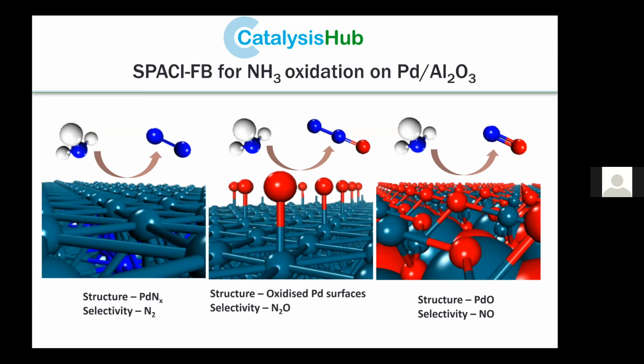It was found in a previous paper that under reaction conditions, palladium nitride is formed and is thought to be the selective phase. This palladium nitride phase is a heteroatom insertion into the palladium lattice, similar to what palladium hydride or palladium carbide is, and it was the first time this was found during this reaction. However, spatially resolved measurement will provide information about what is the true active phase for the system.